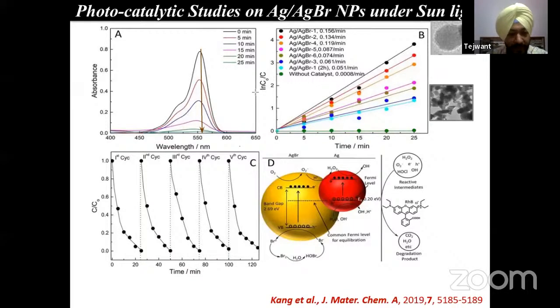One thing, we have prepared the nanoparticles under sunlight, then we have used these nanoparticles as the photocatalyst, that too under sunlight. So we have compared a variety of silver bromide nanoparticles which we have prepared by using different molar ratios of silver and silver bromide. It was found that the nanoparticles which have a Janus shape have shown very high photocatalytic activity.